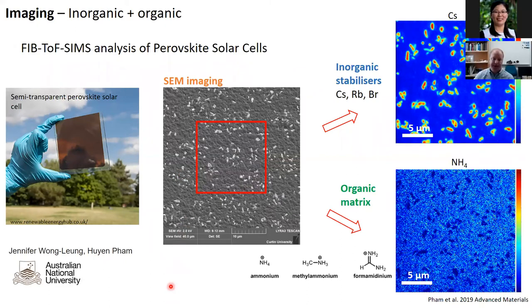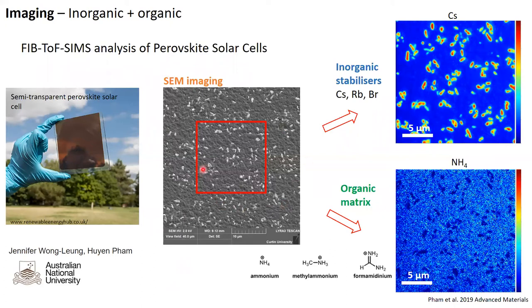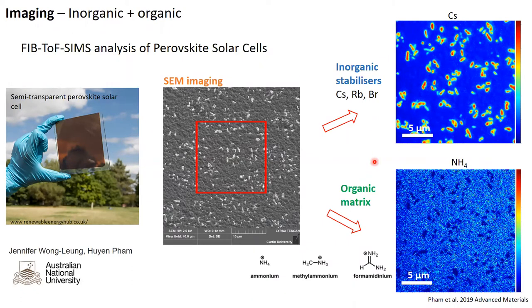In work with Dr. Wong-Leung and PhD student Huyen Pham, we analyzed semi-transparent perovskite solar cells. These have a very fine half-micron thick active surface layer with two major phases: inorganic stabilizers among an organic matrix. The inorganic phase — cesium, rubidium, bromine — is quite easily analyzed by TOF-SIMS. Although gallium FIB-based TOF-SIMS has limited ability to analyze organics because gallium tends to break most molecular bonds, it does preserve some small organic molecules. In this case we were able to map the distribution of ammonium among the inorganics. So we can do some organic analysis, but primarily this is used for inorganic analysis.